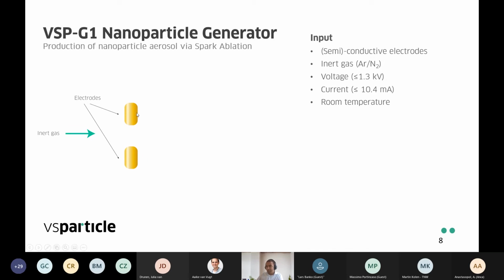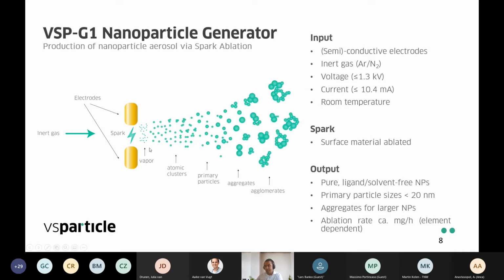So a high voltage is applied between these two electrodes, which leads to a spark being formed. And the spark then ablates or removes a small amount of material from the surface of these electrodes. And this vapor then sinters to form small atomic clusters. These atomic clusters can then form larger primary particles, and these primary particles can aggregate or agglomerate to form even larger particles. So overall, the input is electricity, electrodes, and an inert gas, and your output are pure ligand-free nanoparticles with a primary particle size of below 20 nanometers.